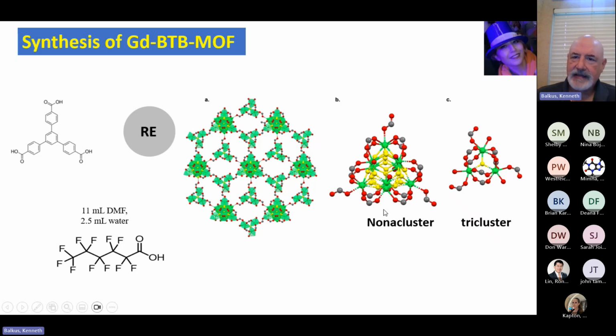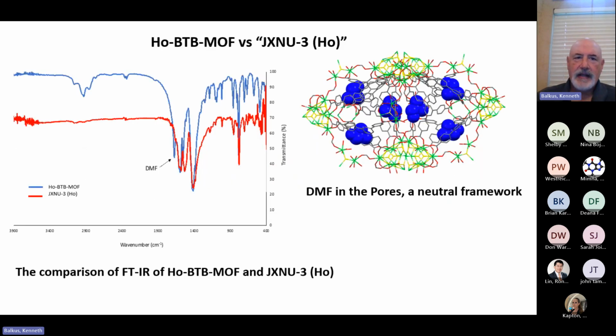And these are not hexaclusters, but nonaclusters. So you've got 9 metal ions in this structure, and there's also a trinuclear cluster as part of this overall structure. Now, interestingly enough, if you try to use the 2-fluorobenzoic acid for this reaction, it doesn't really work. But this PFAS works like a charm. I should point out too that this nonanuclear cluster with a tricluster, these are neutral frameworks. And if you made the oxo version of this without any fluorine, it's a charged framework. And there's a big difference. You can actually find the DMF molecules in the pores, and so we have a neutral structure.